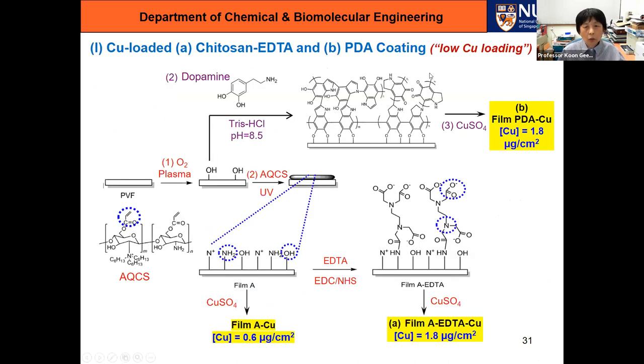So this is the low copper loading surfaces. A number of them is a little bit messy. The top route over here is just to show polydopamine, that's all. So polydopamine on the surface is easily made. We just treat it with a copper salt solution and the copper ions would be interacting with the various functional groups. The bottom route here shows the grafting first of acrylated quaternized chitosan.